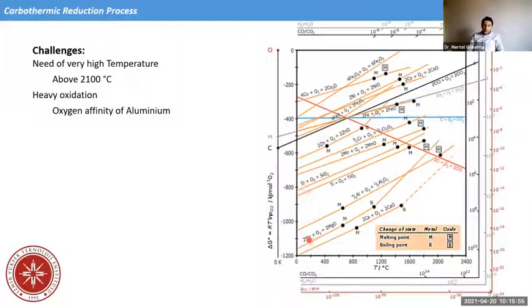And here is the aluminium oxide stability line, and it meets with carbon at temperatures above 2100 degrees Celsius, almost 2500 Kelvin. This is a very high temperature because we need alumina liquid here. So the challenge with the carbothermic reduction process in the case of aluminium is that it needs very high temperature. And this means a lot of cost.